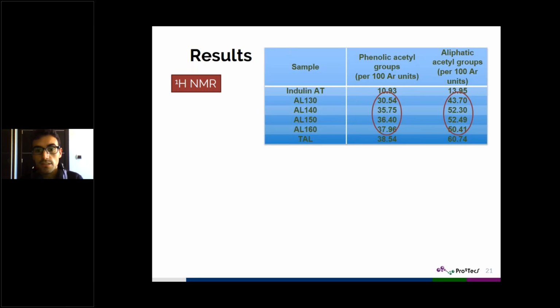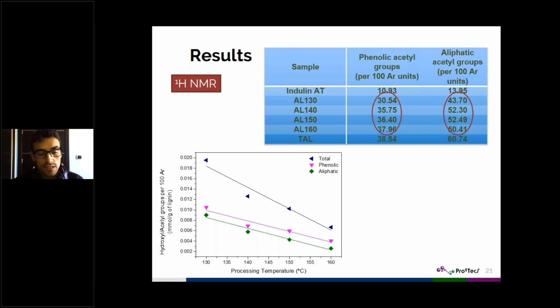Finally, again, it is worth mentioning that the traditional acetylated lignin is the one that shows the highest phenolic and aliphatic acetyl groups concentration. So after this, we wanted to see, can we get a correlation between the hydroxyl group loss and the acetyl group formation with the processing temperature? And in fact, we can obtain that. We can see that we obtain almost a linear trend between that relationship between hydroxyl and acetyl groups and the processing temperature. So the first of our big outcomes of this study is that we can tune the acetylation process just by changing the processing temperature.